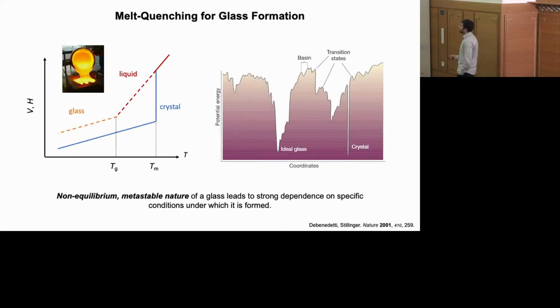And so the synthesis of glasses is a non-equilibrium process. Glasses are metastable with respect to a crystalline state. And the nature and the structure and properties of a glass depend a lot on the process by which it was formed. So exactly how quickly and from what temperature it was quenched in the molten liquid state.